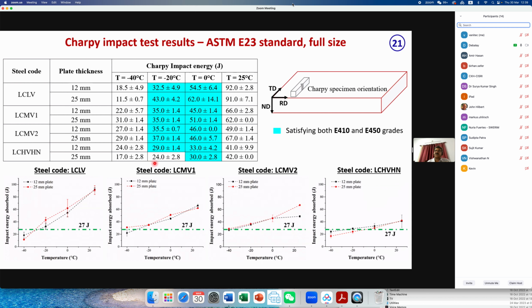but our grades that we are preparing are open induction melting. So we expect in controlled industrial melting, industrial rolling, the microstructure will be more refined, and this value is not very less than 27 Joule. So our expectation is in industrial scale, these values will be very well met to whatever is the requirement. You can see the transitions -20, more or less these are meeting the minimum requirement, barring this high vanadium, high nitrogen one, where we are getting the maximum strength level.